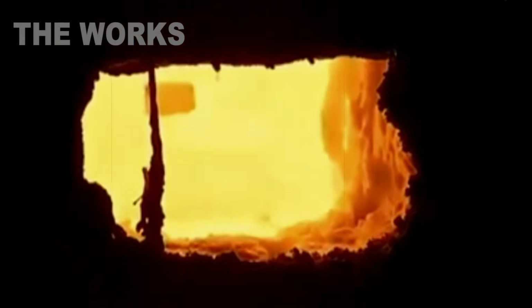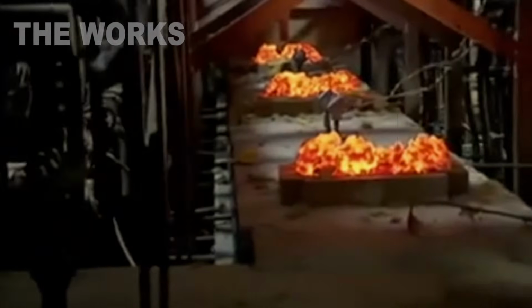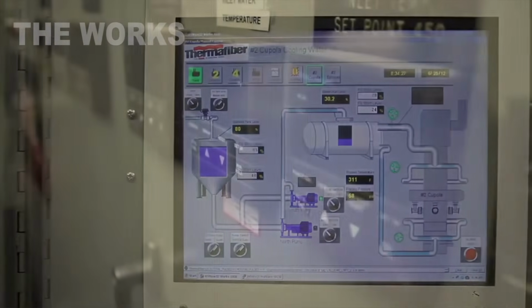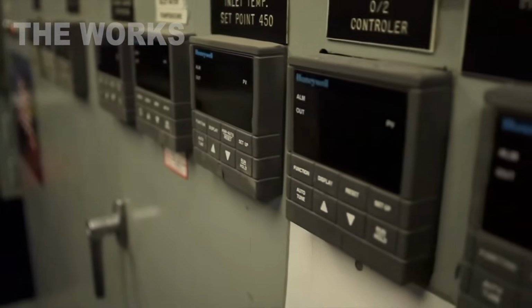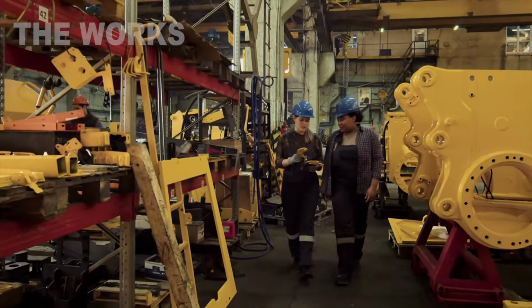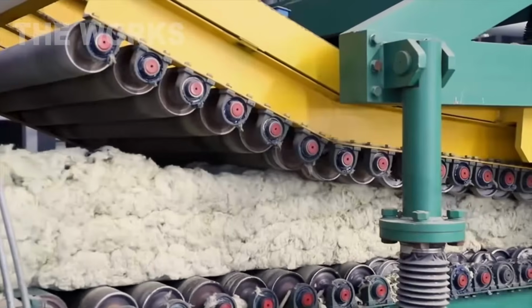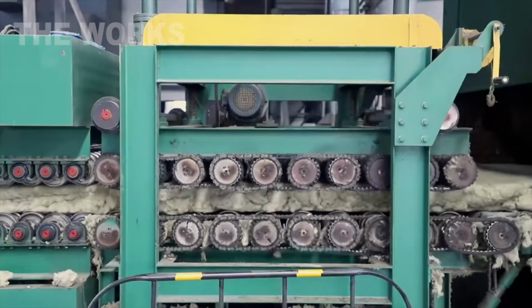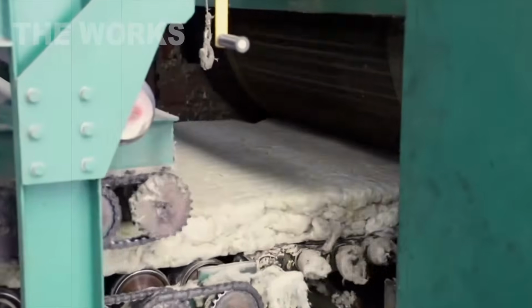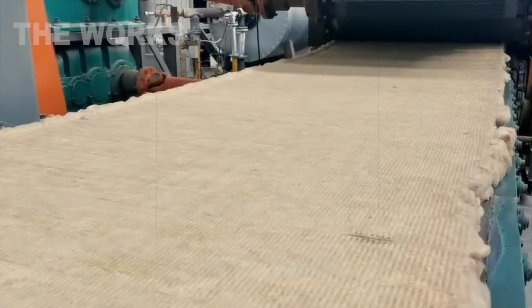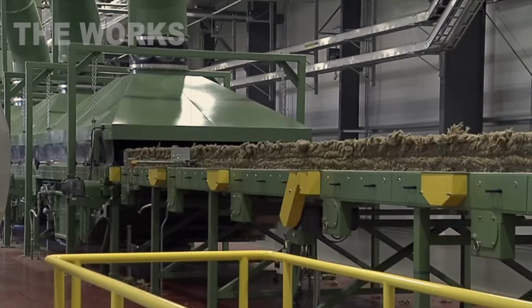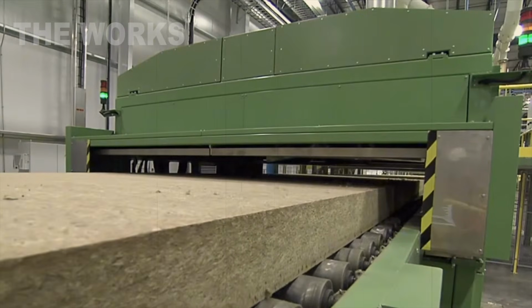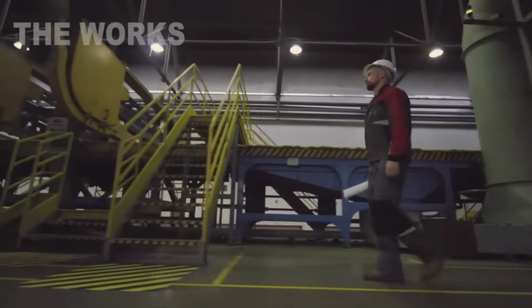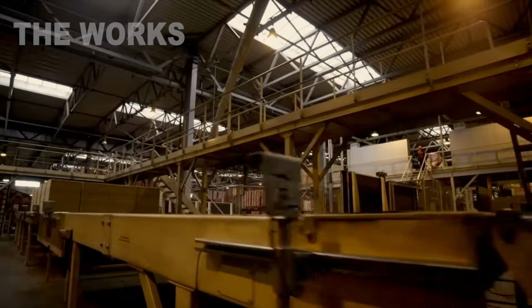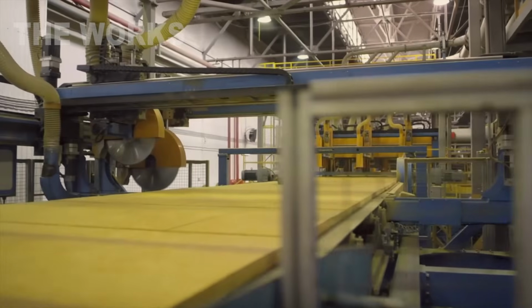That is, its molecules cross-link into a robust three-dimensional network, transforming into solid plastic that permanently bonds the stone fibers at their intersection points. It's within this oven that mineral wool acquires its final properties. It becomes resilient, capable of recovering its shape after compression. During this process, the resin often changes color, lending the finished product its characteristic yellowish-brown hue. From the other end of this gigantic toaster oven emerges no longer a loose carpet, but rather a solid, springy mat of specified thickness and density.